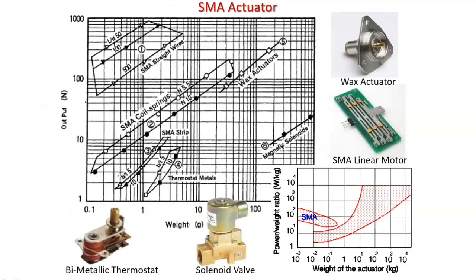And if you were to compare these actuators and summarize this, the wax actuator is the simplest. It's one end of the spectrum, in which you start with a wax which melts in a cylinder, and there is a piston which it drives. So on melting, you have a volume change, and one third of which will express itself as a linear displacement. This thing being very small, you can imagine how much displacement there is after all, and it's going to be very, very small.